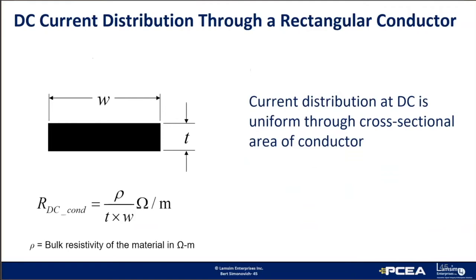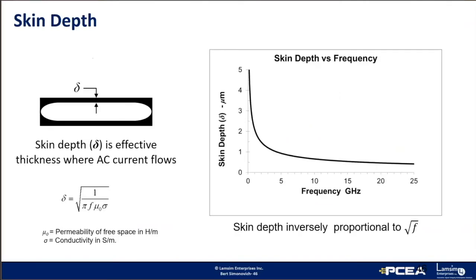Given a conductor with a width and thickness shown here, current is uniform through the entire cross-sectional area. The resistance per unit length can be easily calculated by this equation, given the resistivity of the material. But above 10 megahertz or so, AC current starts to flow mainly along the skin of the conductor. The skin depth is the effective thickness where AC current flows and is calculated by this equation. And as you can see from this graph, skin depth decreases inversely proportional to the square root of frequency.